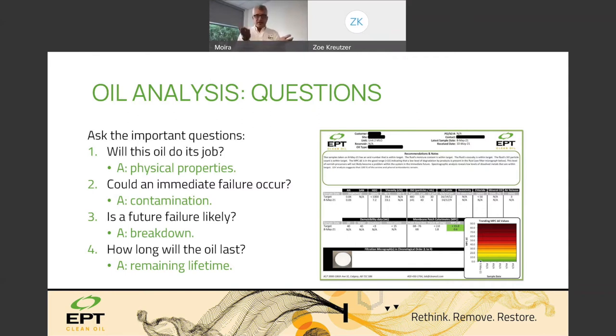You see these target values that are listed here? These target values should actually be new oil standards in combination with ASTM guidelines. But quite often what happens is the lab will select a reference point for you that may be inaccurate or just incorrect. I always like sending my own sample in from a new drum and testing that, and then using that as my in-service guideline as compared to new fluid. And then I will look at the ASTM guidelines to set warning limits. Quite often I see, I'd say a third of the time, the number one problem with lubricant analysis is that the reference point doesn't exist or it's incorrect.